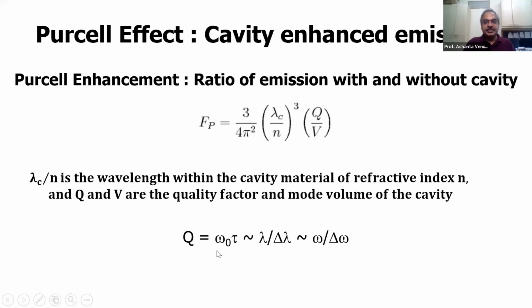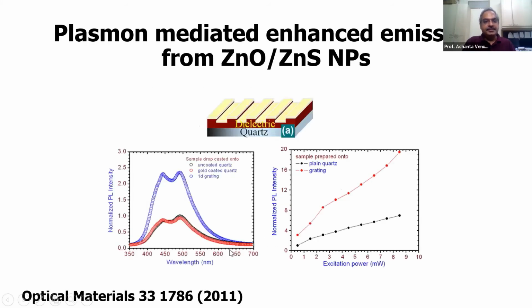So this Q is in terms of the cavity mode lifetime and the cavity resonance, omega 0 times tau, or in the spectral domain, we measure the resonant wavelength lambda and the line width delta lambda. And from that we estimate the Q factor. Right? This is one example of how the emission can be enhanced. So this is a plasmonic structure where a dielectric has been patterned to have a periodic grating-like structure on which the zinc oxide, zinc sulfide nanoparticles have been spin coated.